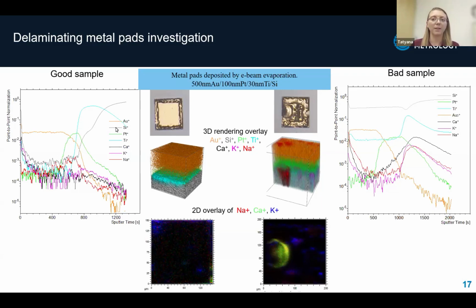The depth profile clearly shows distinct transition within each metal layer. You can see this both in the spectra and in 3D reconstruction. There the layers are well separated. Now compare that to the bad sample on the right. Even in the optical image we can see,